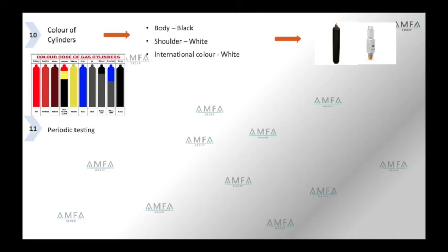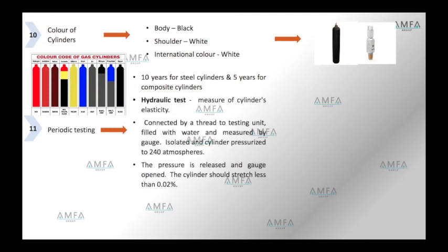Regarding the periodic testing of the cylinders, the cylinders are expected to have a longevity of 10 years for steel cylinders and 5 years for composite cylinders. A hydraulic test is done to measure the cylinder's elasticity. It has to withstand high pressure, so it is connected by a thread to a testing unit, filled with water and measured by a gauge, isolated, and the cylinder is pressurized to 240 atmospheres. The pressure is released and the gauge opened. The cylinder should stretch less than 0.02 percent.